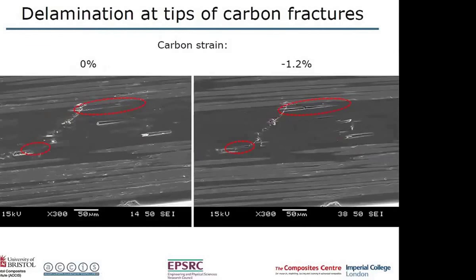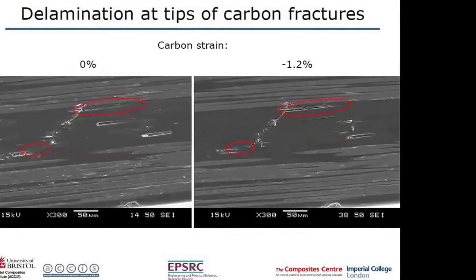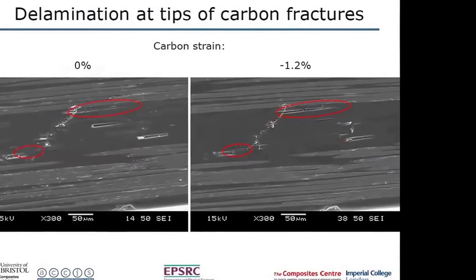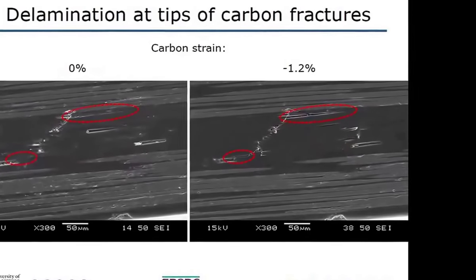So you can see here, this is the fragmentation crack. You see the fibers have broken at an angle. The angle is a bit variable, but it looks a bit like a shear crack. But then at the top here, if you compare this one with over here, you see that it's opened up. There's a bit of a delamination crack here, a bit down here. So that's what's happened. The fibers are broken in compression, and because of that angle, they're able to force each other apart to get a little bit of localized delamination.